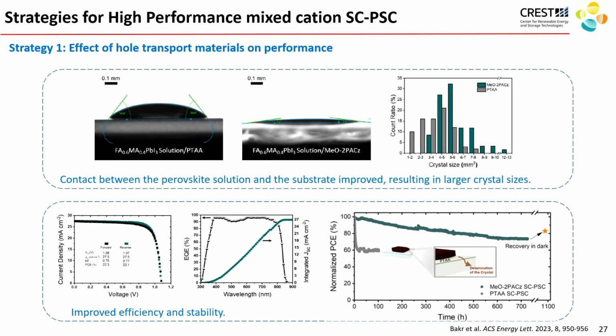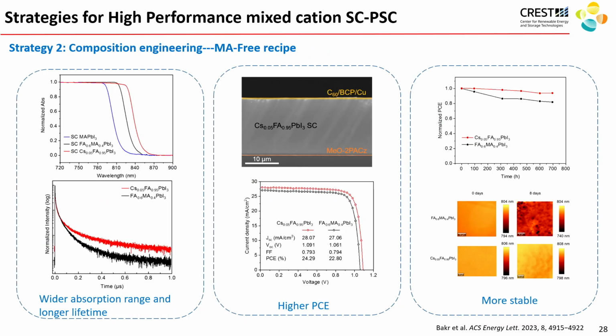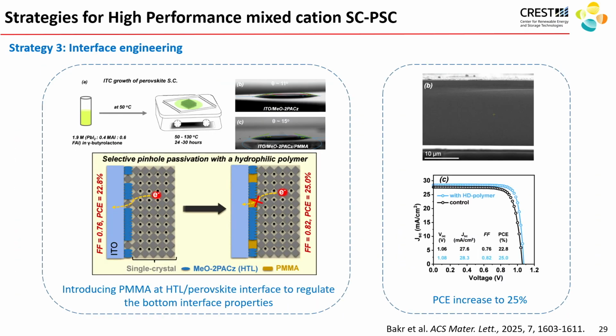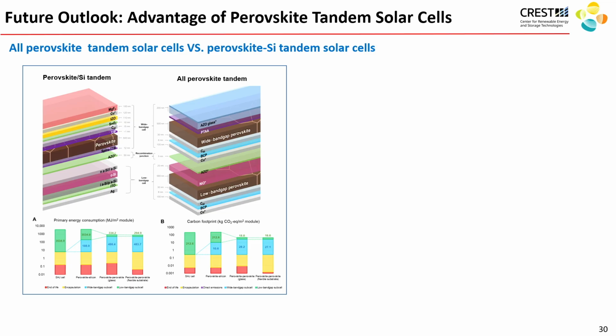we spent a lot of time working on single crystals, and because the charge diffusion length in perovskites is so long, we were able to make single crystals that ranged anywhere from 20 microns to 100 microns that were still almost as efficient as thin film devices that were 100 to 700 nanometers. That was very important for us, and I'm not going to go too much over the different device configurations that we've done, but we've found ways of growing crystals without volatile organic cations and improving their efficiencies and their stabilities over time. Now I'm just going to go quickly over, just to tell you a bit about tandem devices.